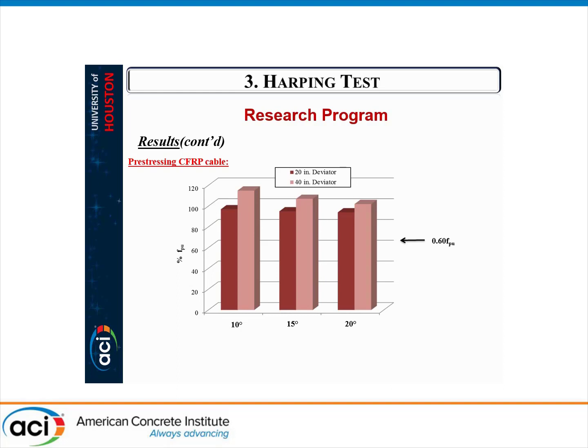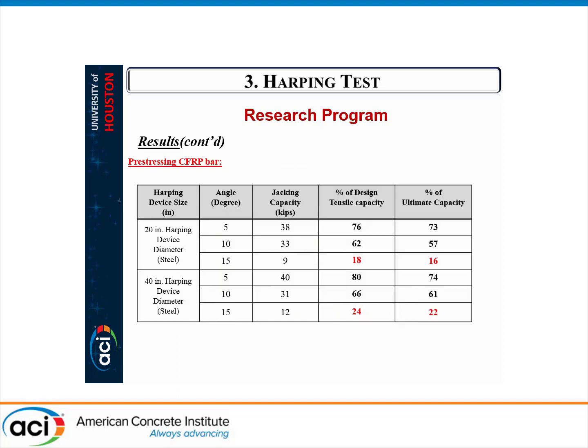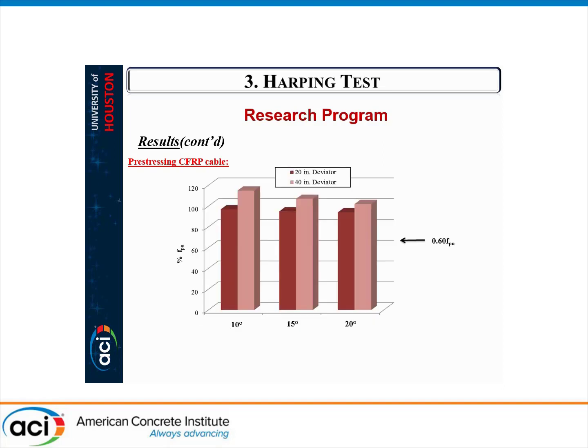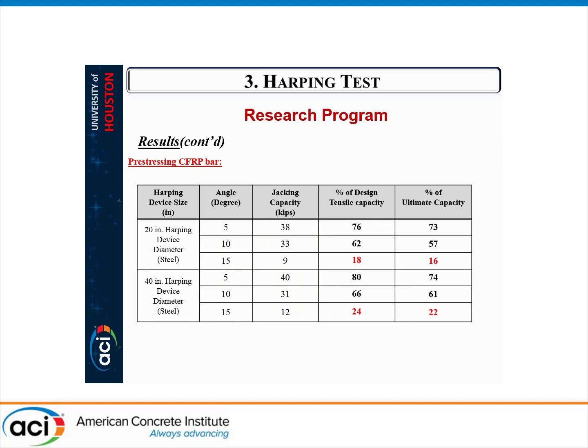And here is another representation of the results. And for CFRP bars, we also conducted these tests with the newly developed harping devices. By having the 5 and 10 degree harping angle, we reach up to 76 and 80% of design tensile capacity, which was a big improvement, and we were able to avoid the premature failure of CFRP bars. But under a higher harping angle of 15 degrees, we still experienced the premature failure and significant reduction in the tensile capacity.